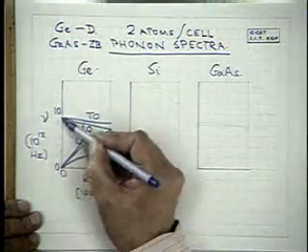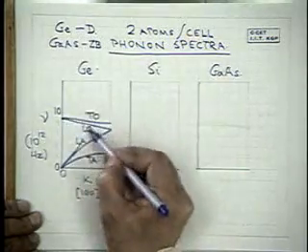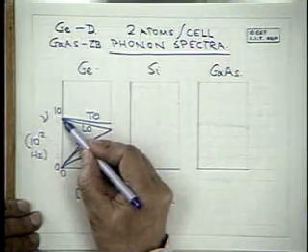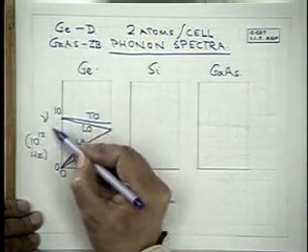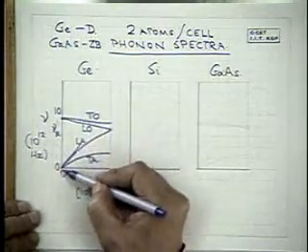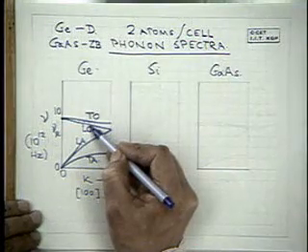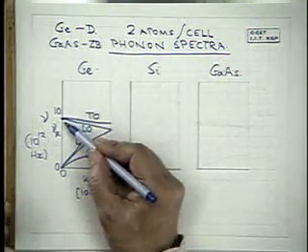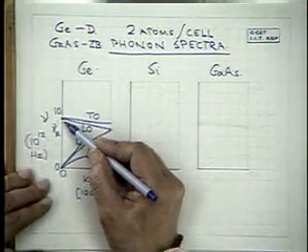The frequency here at k equal to 0, notice that the TO, LO phonons are degenerate here. This is nothing but the Raman frequency, because when light comes in, TO or LO phonons are excited, and there's a loss of energy, so there's this Stokes shift, and the scattered photon has energy less than this.